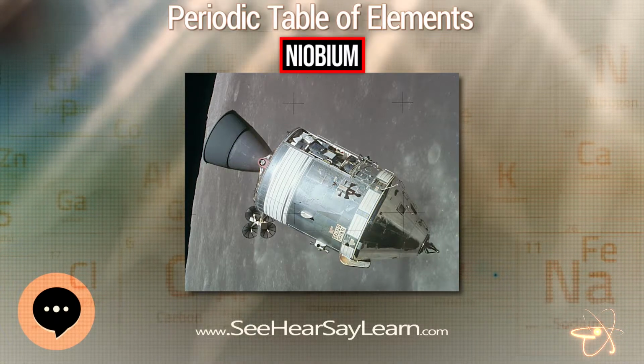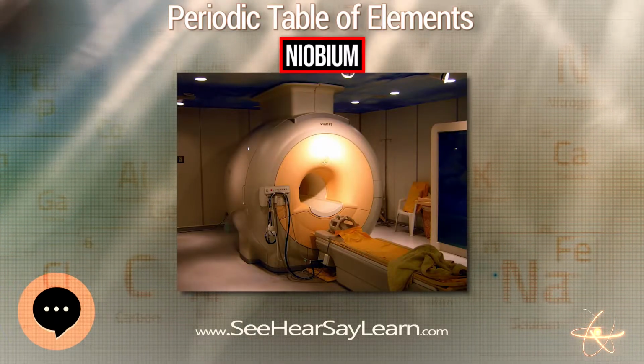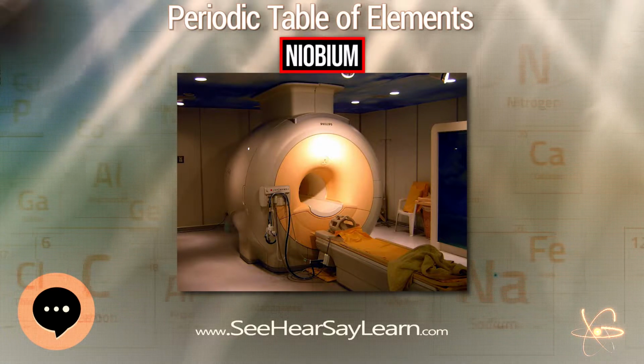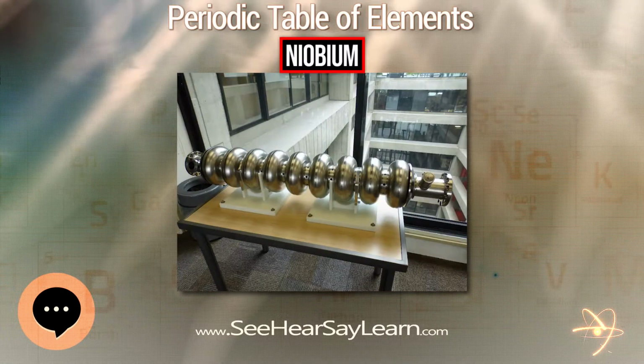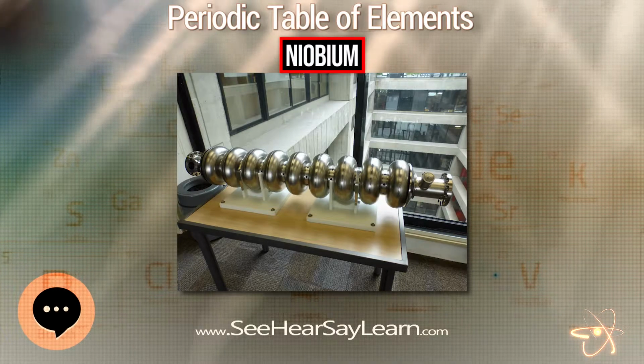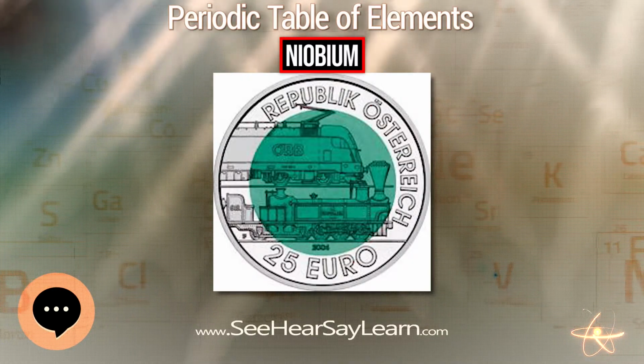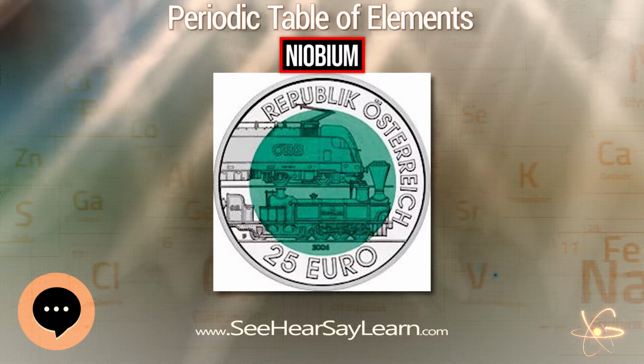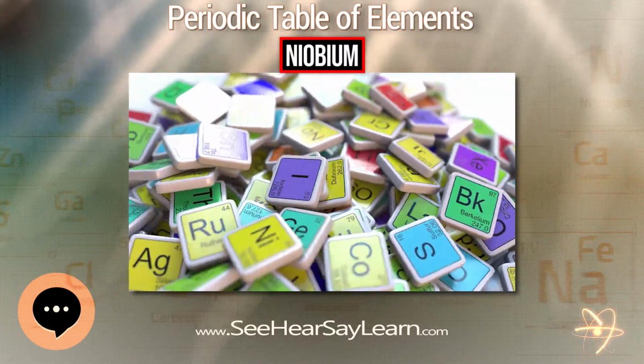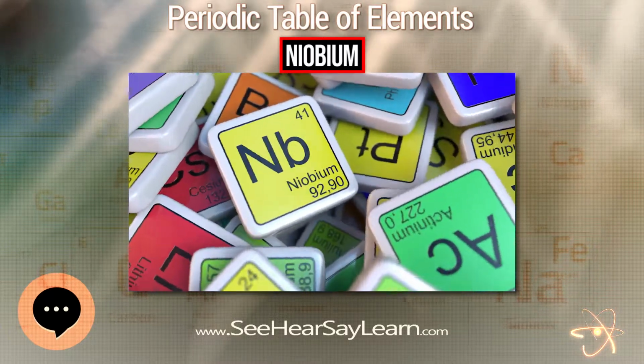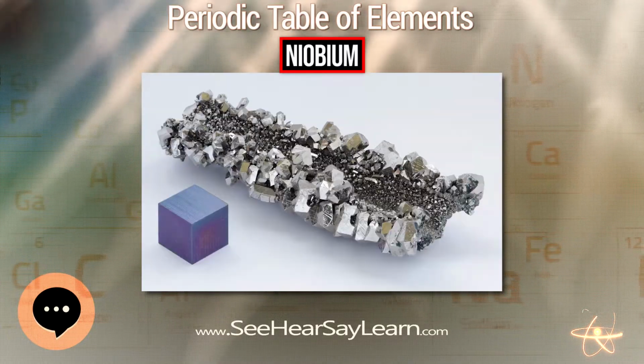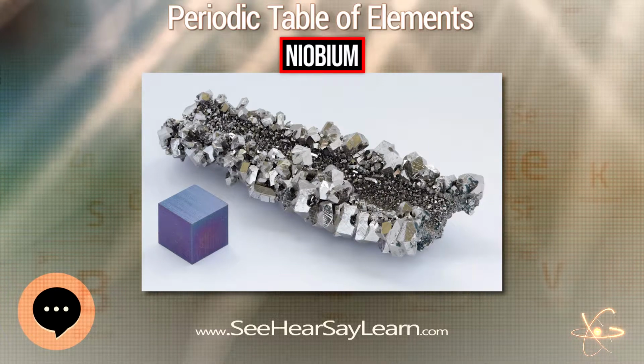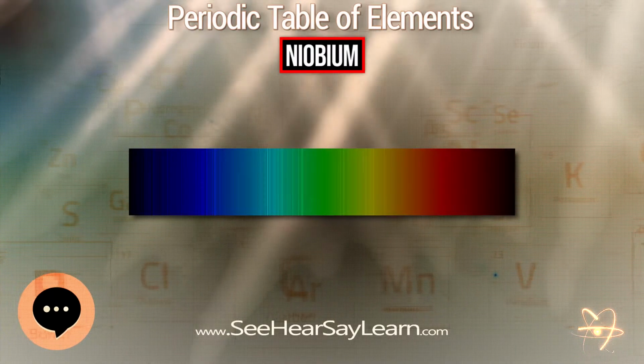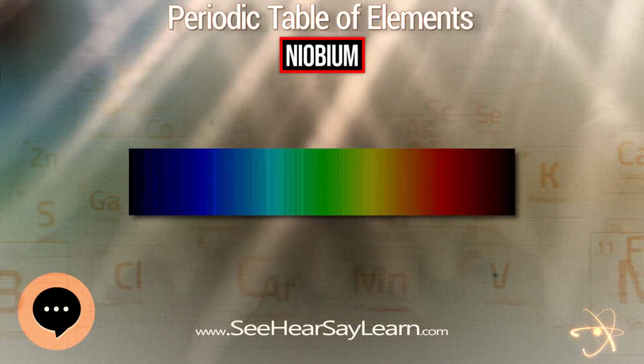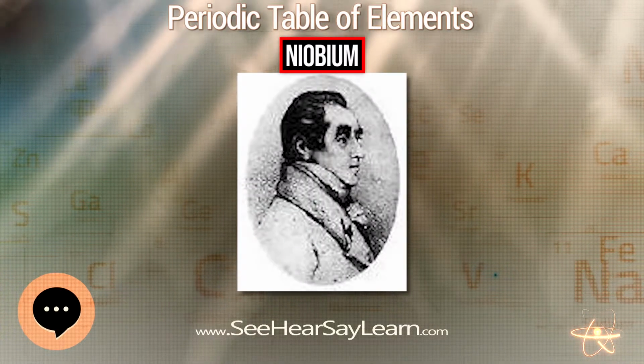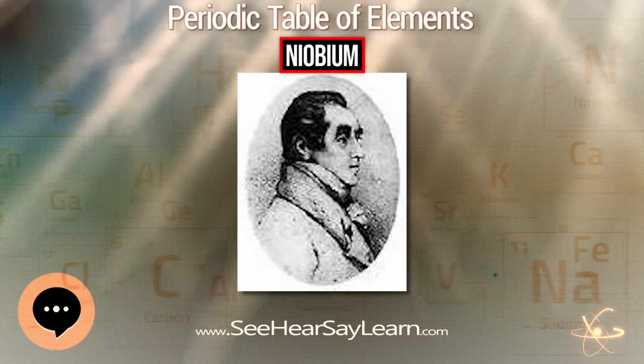After the separation from the other minerals, the mixed oxides of tantalum Ta2O5 and niobium Nb2O5 are obtained. The first step in the processing is the reaction of the oxides with hydrofluoric acid. The first industrial-scale separation, developed by de Marignac, exploits the differing solubilities of the complex niobium and tantalum fluorides, dipotassium oxypentafluoroniobate monohydrate (K2[NbOF5]·H2O) and dipotassium heptafluorotantalate (K2[TaF7]) in water. Newer processes use the liquid extraction of the fluorides from aqueous solution by organic solvents like cyclohexanone.